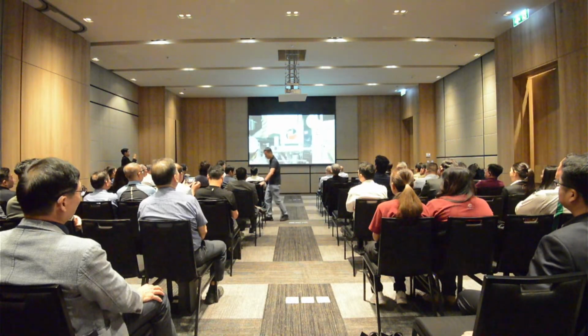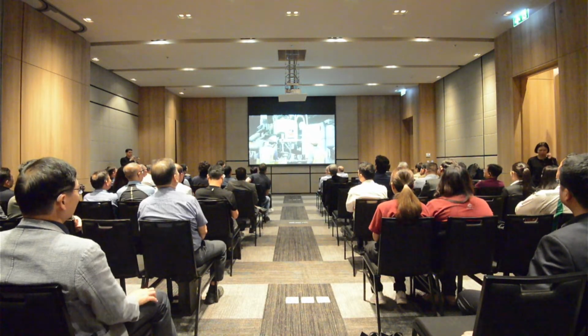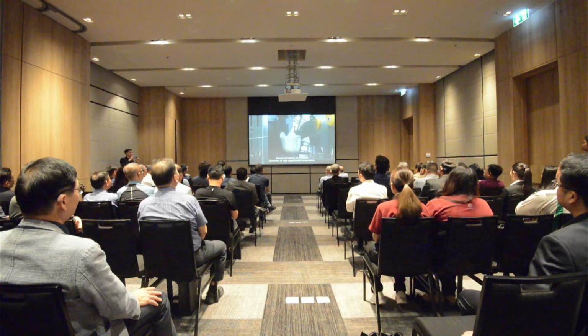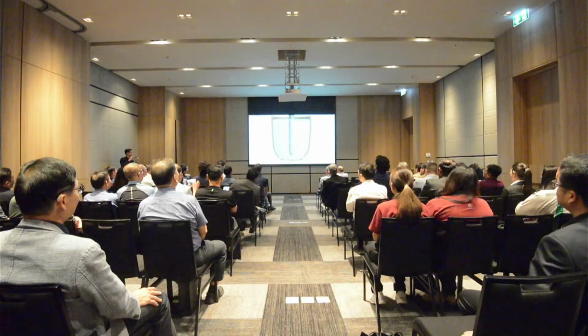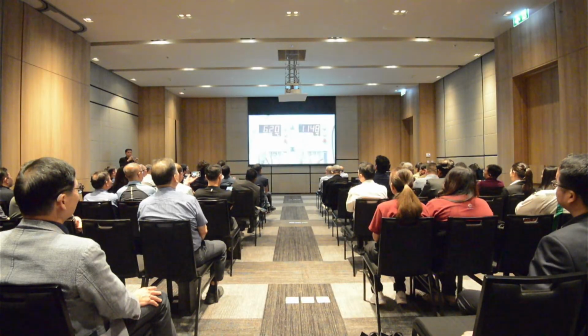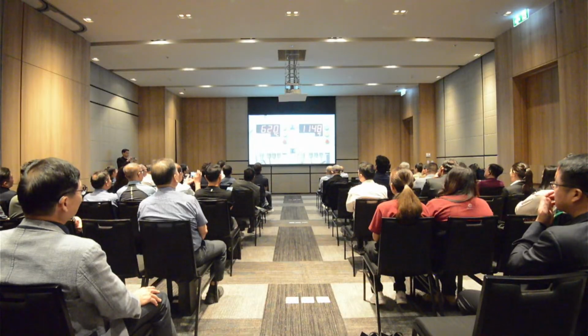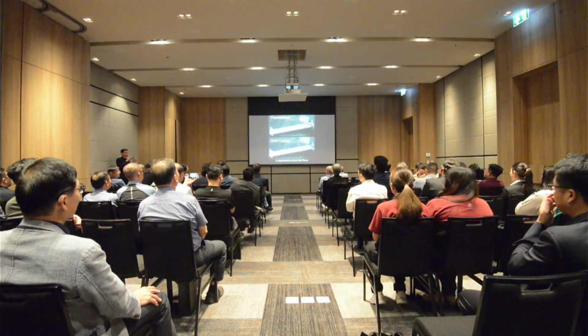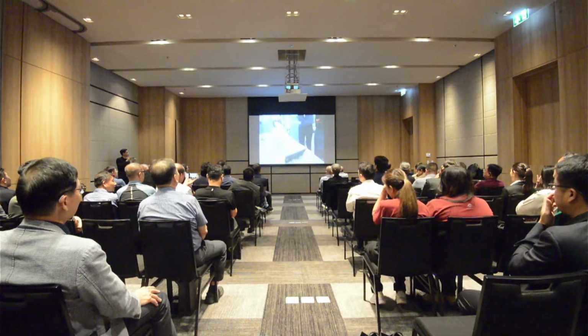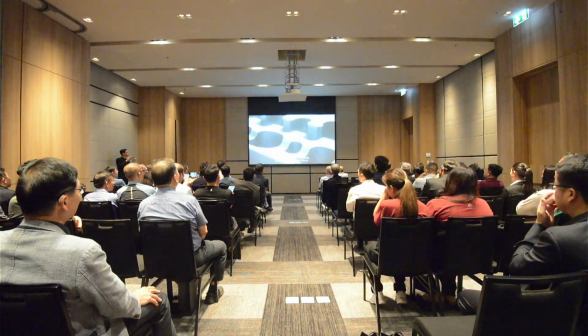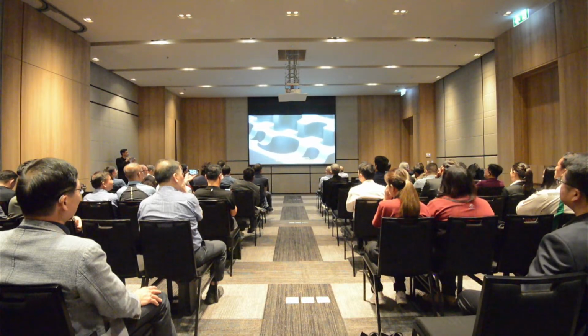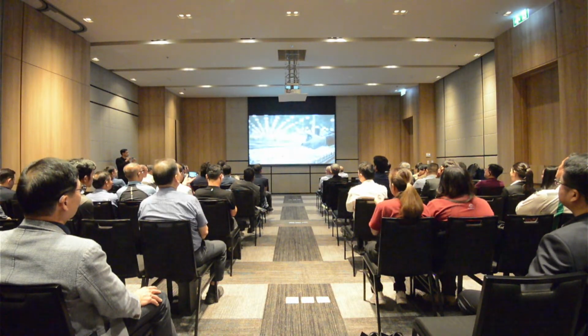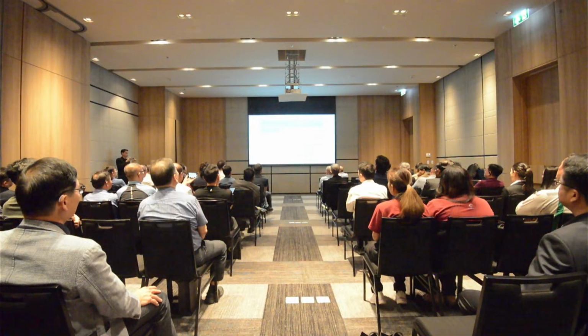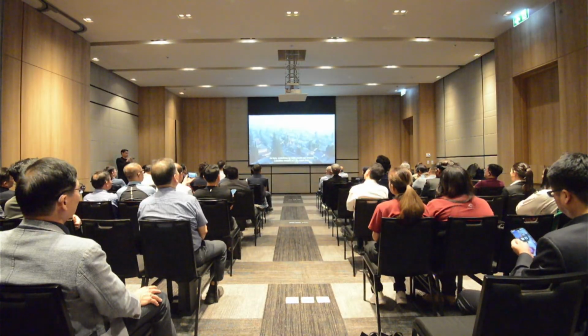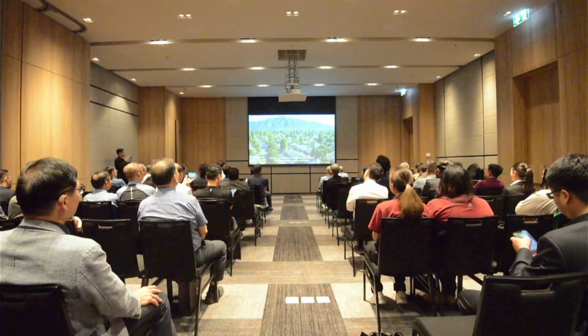Introducing GISS technology, short for gas-induced semi-solid slurry. Instead of melting and holding aluminum at high superheated temperature, GISS gently stirs the metal with fine inert gas bubbles at a lower temperature, typically below 620 degrees Celsius. The result? A semi-solid slurry that flows more like warm milk than water. Smoother, calmer, more controlled. It fills molds with less turbulence, fewer defects, and lower stress. That means stronger parts, less scrap, longer mold life, reduced spray and water treatment usage, shorter cycle times, and significantly lower energy consumption. In fact, switching to GISS could cut around 3 million tons of carbon dioxide each year.